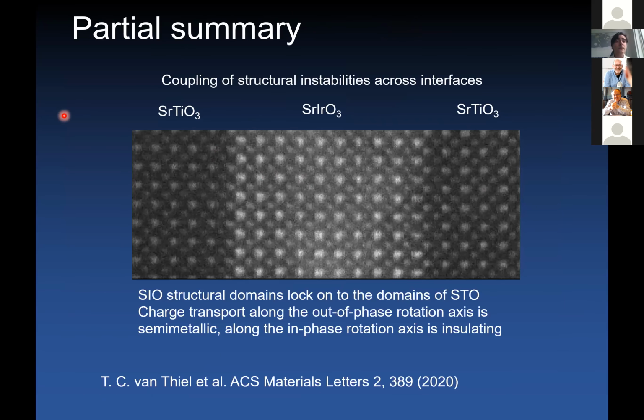Okay, so this brings me to my second partial summary. So I've shown you that at these strontium iridate strontium titanate interfaces, you can have a coupling of structural instabilities across the interfaces, and the strontium titanate domain structure is really providing a template for the domains of strontium iridate and dictating a transport anisotropy in the system. This is very interesting to explore for nanoscale transport phenomena. So now we really have an interesting playground in which we can define this current path that in principle should also be associated with antiferromagnetic order in the insulating directions.